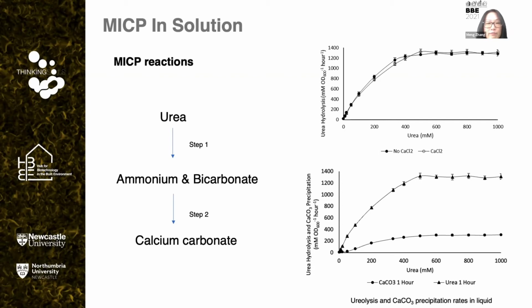She did some investigation in the liquid solution, and he tested the impact of various chemicals on urease activity. Clearly, the top right figure shows the presence of calcium ions has no impact on the urea hydrolysis rate. Then he investigated the rate of urea hydrolysis and the calcium carbonate precipitation.